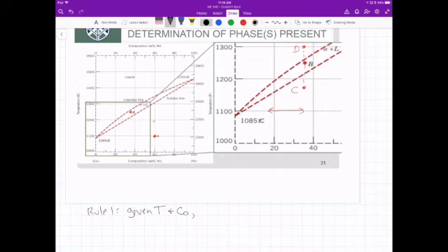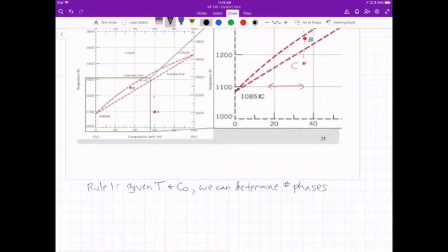Okay. So the first rule, given a temperature and initial concentration, we can determine the number of phases. All right, so let's use point A as our example. Point A, we are given a temperature, right? To get to point A, it has to be 1100 degrees. So temperature equals 1100 degrees Celsius. And our initial concentration, we can read that off of the graph at any time. That is our initial, right? That doesn't change. So our C naught is 60, and look at my x-axis, 60 weight percent nickel. So how much copper do I have? Subtract it from 100, 40 weight percent copper. You can always calculate the other component just by subtracting from 100.